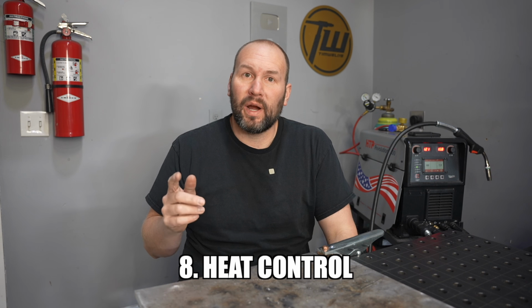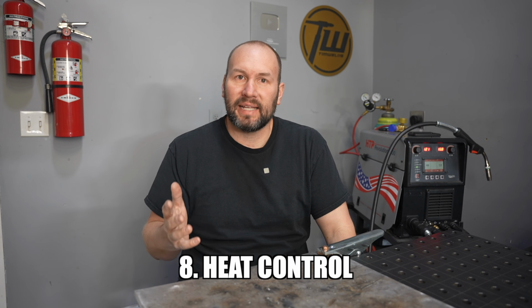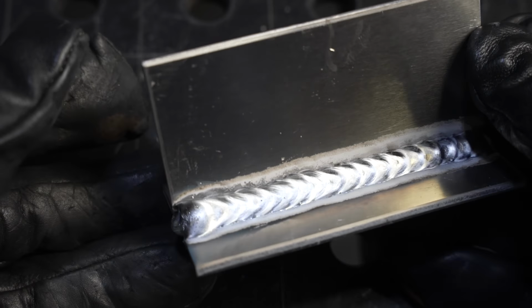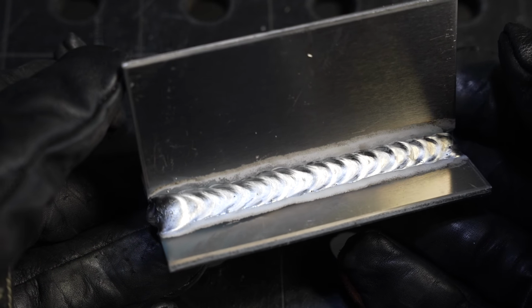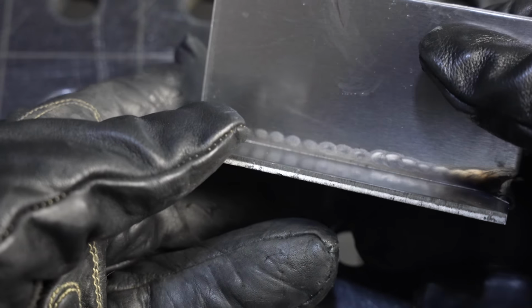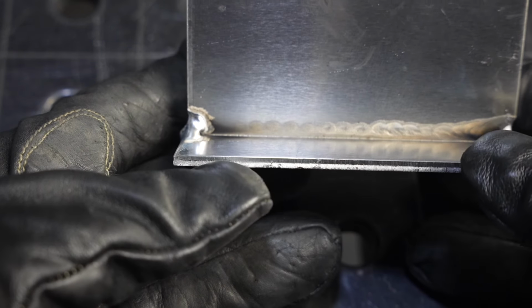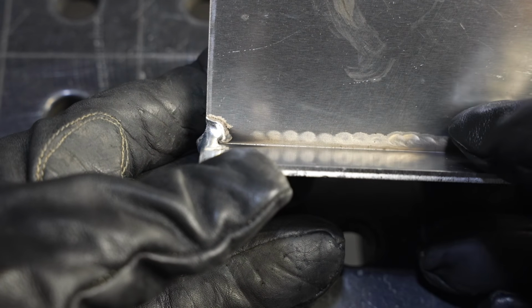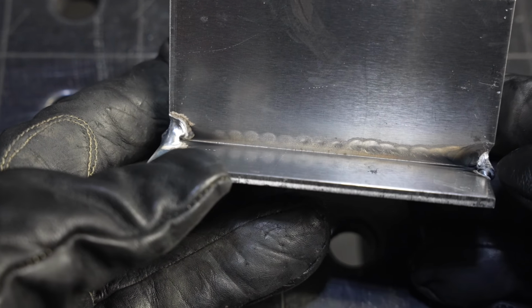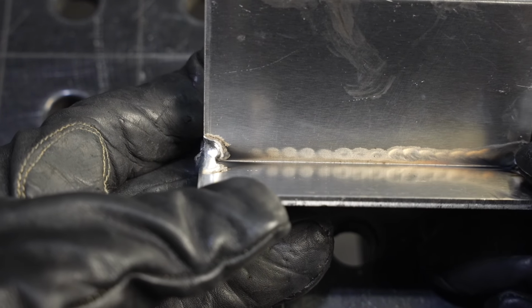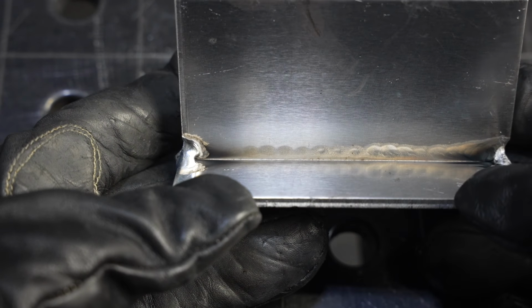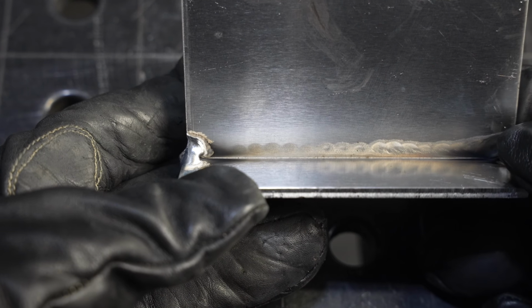Now it's important to be aware that your settings might not be ideal at the start and end of your weld because aluminum conducts heat so well that heat can run up ahead of you. And on these little coupons, that's really exaggerated. You can see if we look at the backside, just how much more heat you get at the end there. So the settings are almost too hot at the end and too cold at the start. So you really need to find some middle ground. A little preheat can help, and some advanced settings on advanced machines can also help with that, but it's important to be aware of.